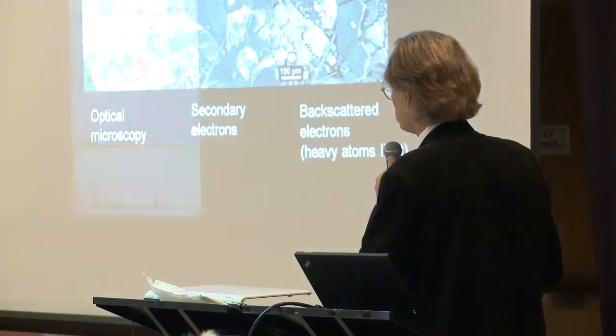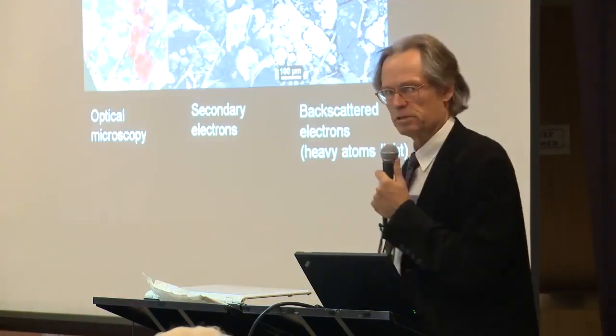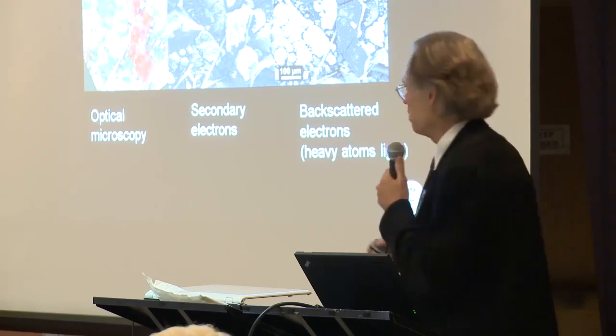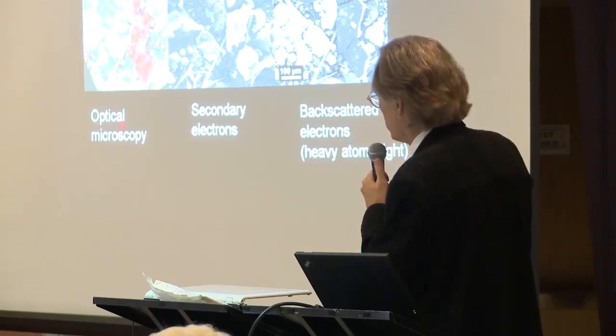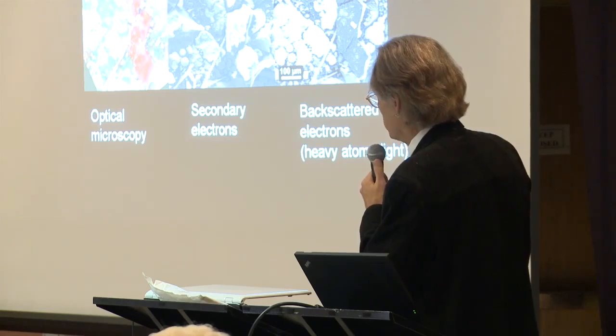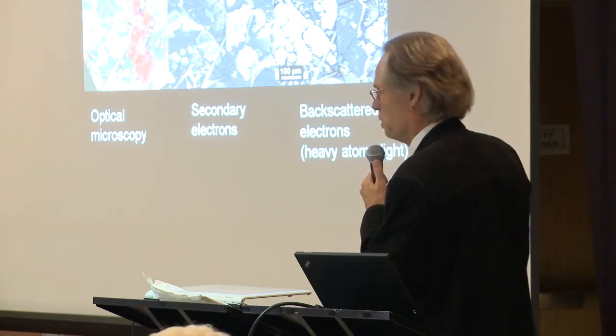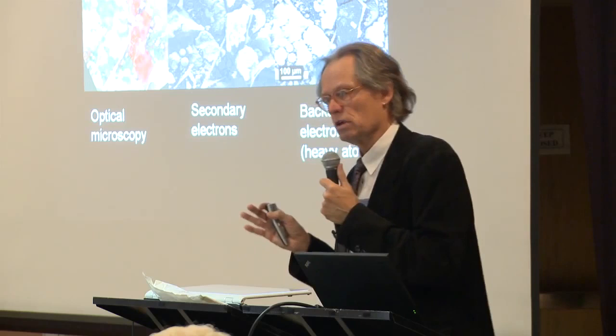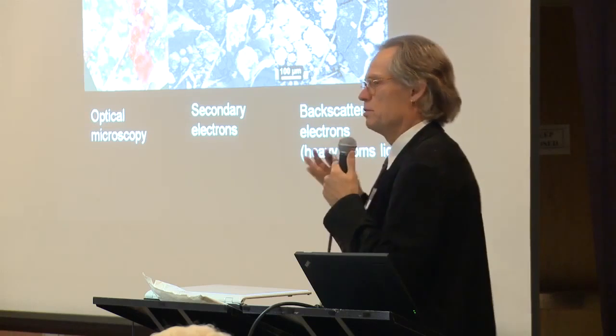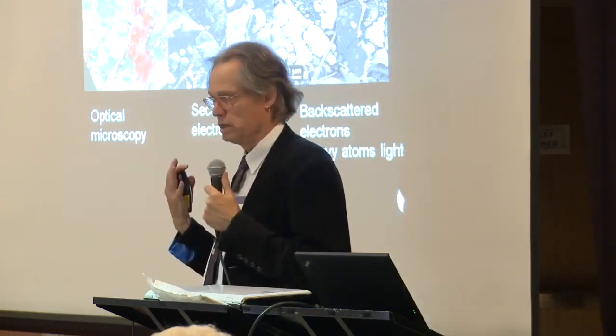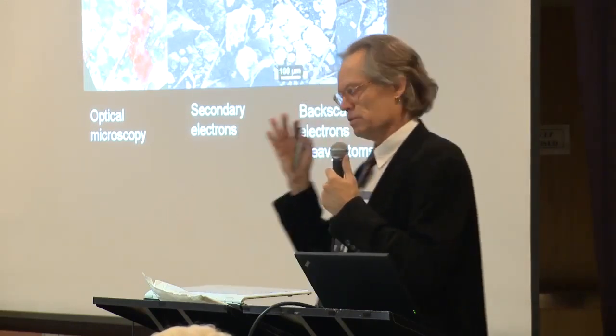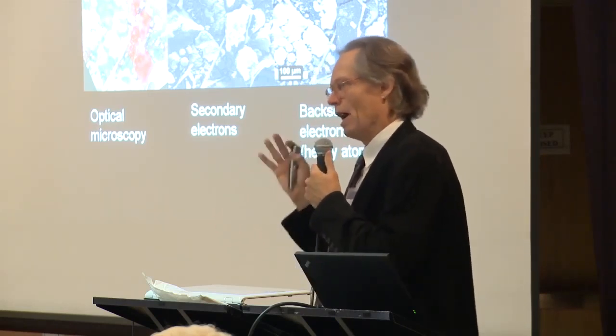We are also using another technology called energy dispersive spectroscopy, which Kevin already has mentioned. The trick is that you direct an electron beam, like the laser beam here, on a specific spot. And this we can do with an accuracy better than 1/10,000th of a millimeter. We can hit a specific spot with an electron beam, and the material responds by sending out X-rays. And these X-rays you can analyze into a spectrum, and from that spectrum you get specific information of which elements are present in the spot you hit with the electron beam.